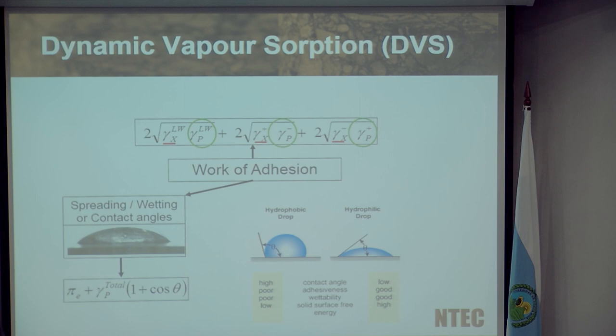In other words, there's no gap or relationship between the probe gas and the aggregate. If that's the case, your cos theta in your particular equation, because your contact angle is zero, comes out as one. Therefore, the only thing that you've actually got to measure is some form of pressure. Your pressure that is being used to force that probe gas to cover your aggregate is the only unknown in this particular calculation method. If we know what the three components of our probe gas are, then by using a matrix calculation, we can work out what our aggregate properties are.